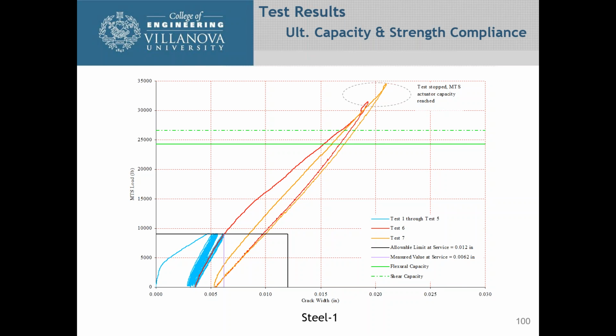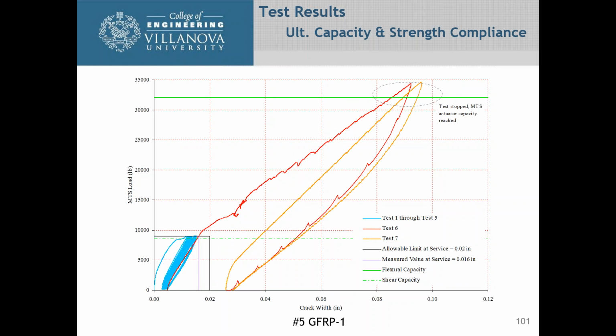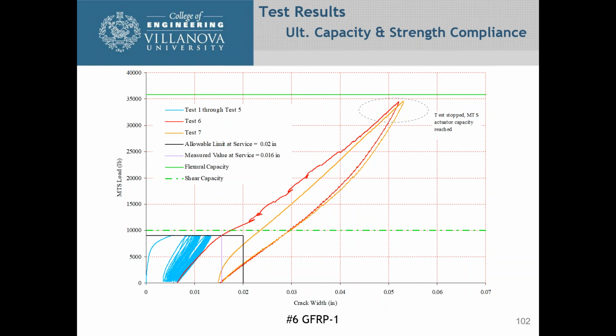Looking at the ultimate capacity, you can see that the dashed line was the shear capacity, the solid green line is the flexural capacity, and we took the actuator almost up to 35,000 pounds. On one of them, we really pushed it to see if we could get to failure, and we didn't get to failure with any of the steel ones. For the number 5 GFRP bar, the solid green line is at about 32,000 pounds, and the failure for the shear is at about 8,000 pounds, and we were able to load it much higher than that. The same is true with the number 6 bar.